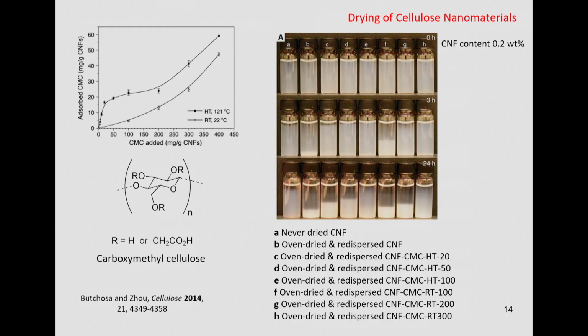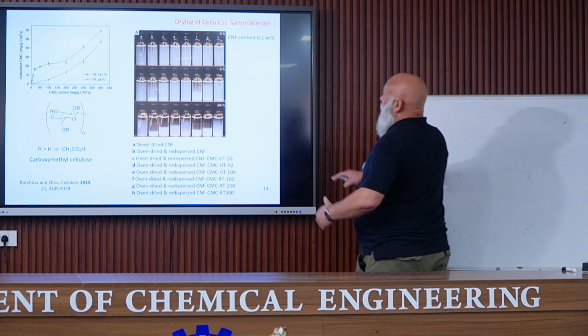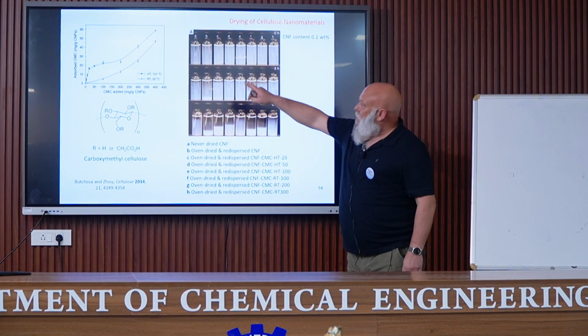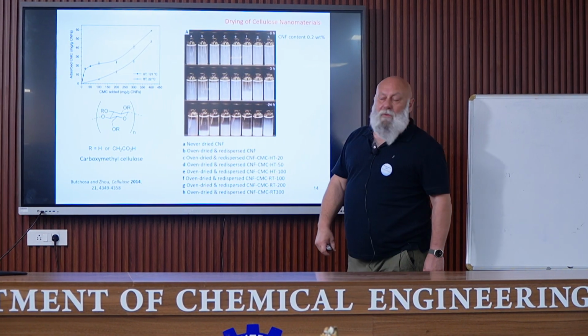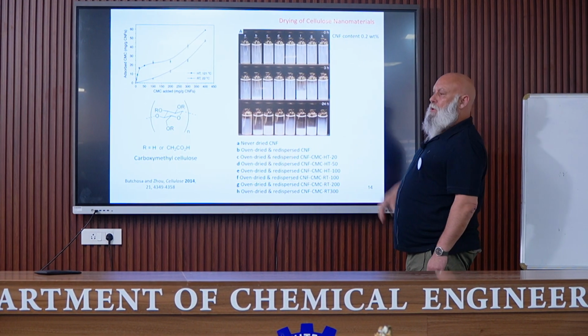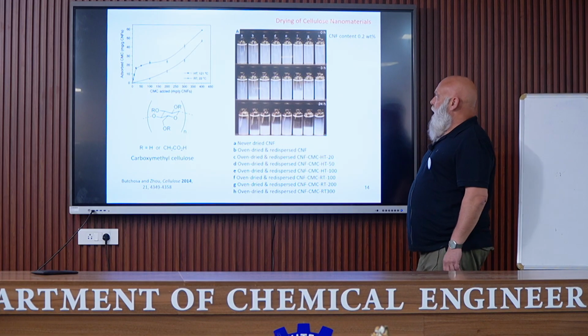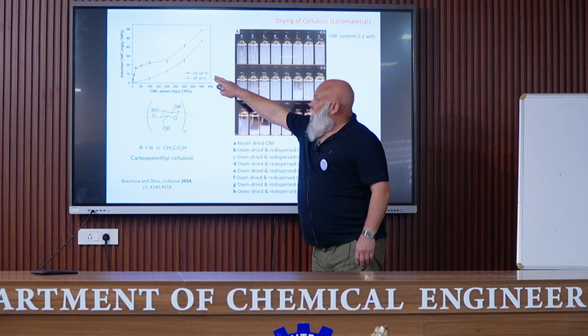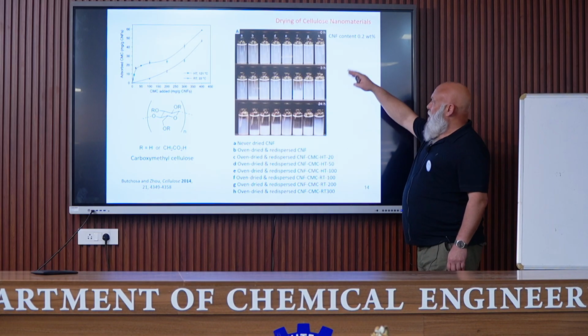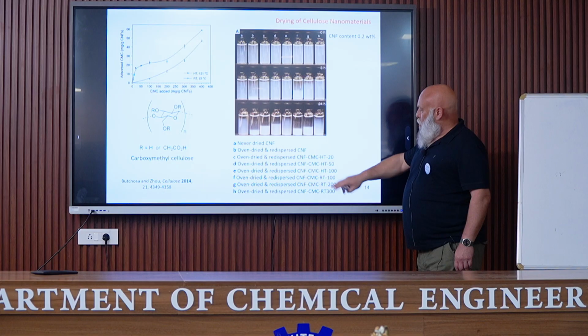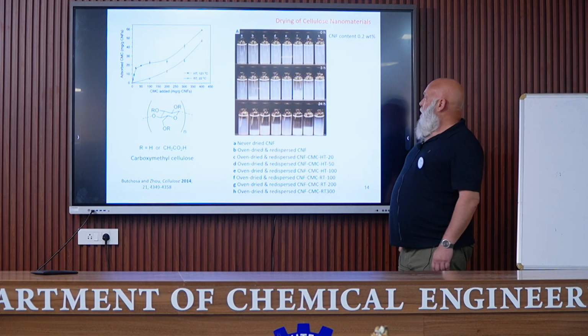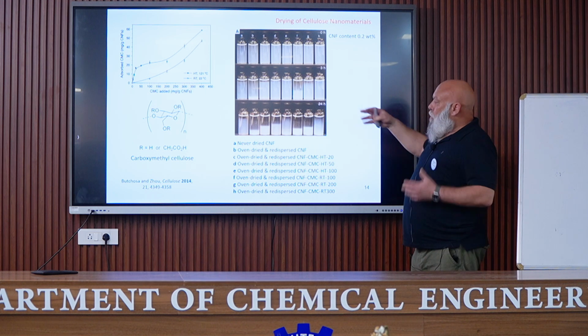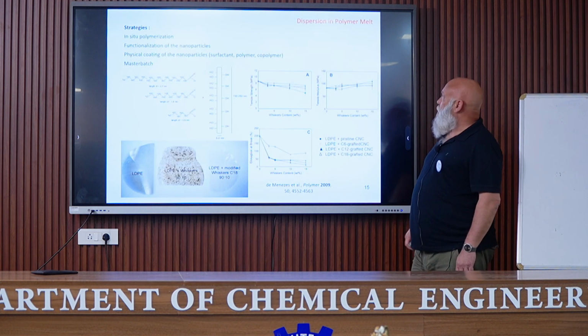This is another example in which the strategy is the same, but in this case, carboxymethyl cellulose was used as a capping agent. So it prevents the aggregation. Again, I will not detail everything, but you have here the adsorbed amount of carboxymethyl cellulose as a function of the carboxymethyl cellulose that has been added to the dispersion. It was performed at 2 temperatures, and we have these different elements here at high temperature, room temperature, and with different amounts of carboxymethyl cellulose. So globally, we have an improvement in the dispersion.